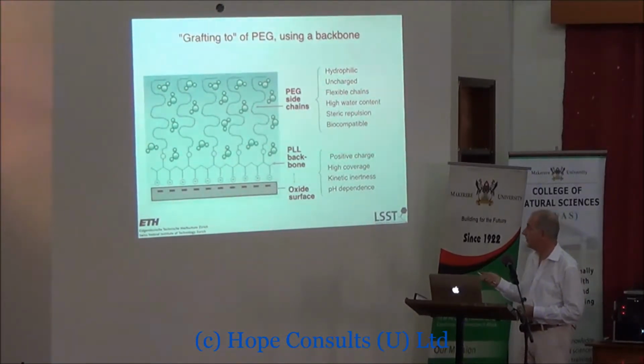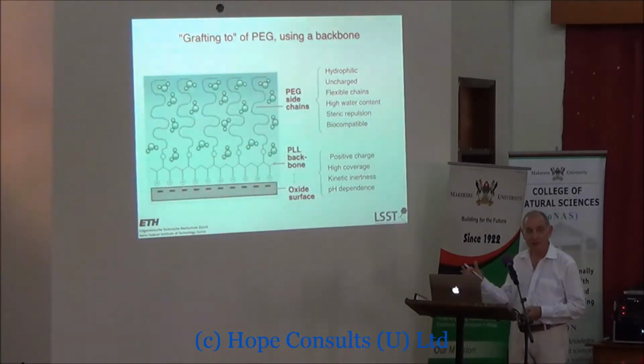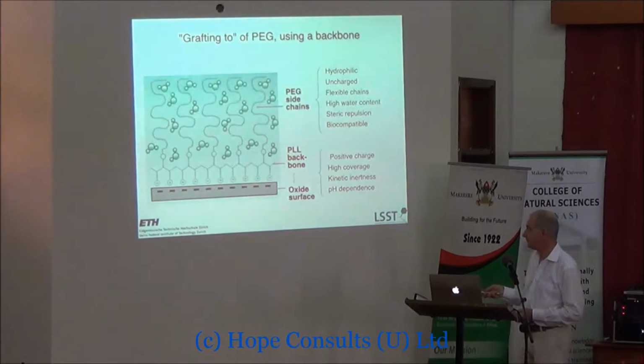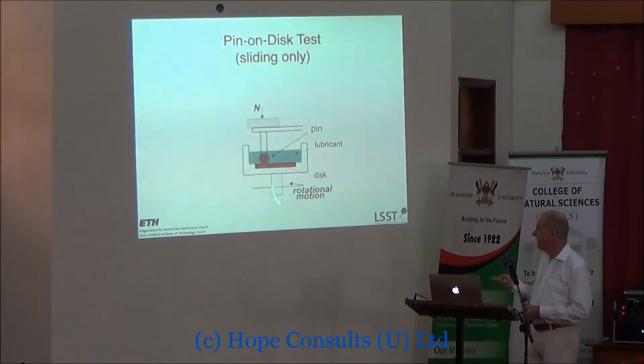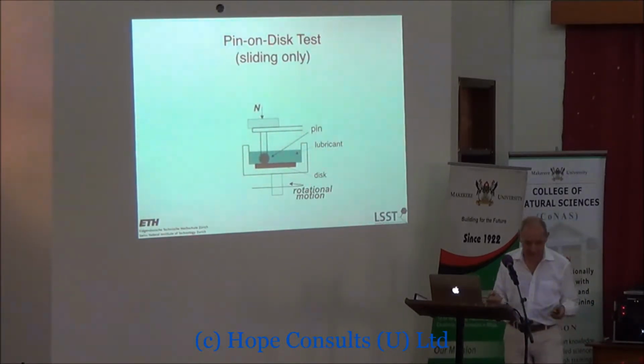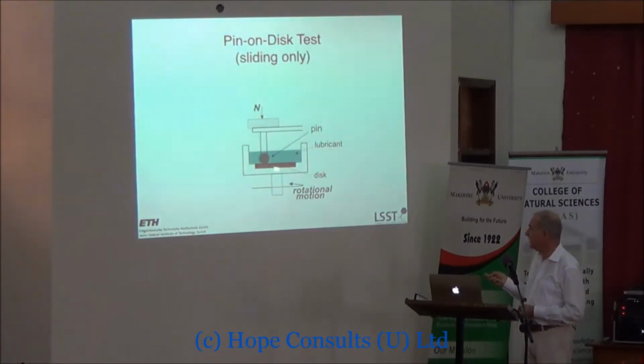And it has lots of interesting properties. It's biocompatible. Proteins won't stick to it, which means cells won't stick to it either. It's a way of making non-fouling surfaces, for example. And it's lubricious, which is why we got interested in it. Now, here's a very straightforward tribological test called the pin on disc test. We use it for testing lubricants, measuring friction. And so we take our lubricant, we put it on top of the disc, and then we slide a pin on it by rotating the disc underneath the pin. We put a load on it, N, which we can do with a dead weight, for example, and then we measure the friction force with a strain gauge as we rotate it. Very standard friction measuring test.